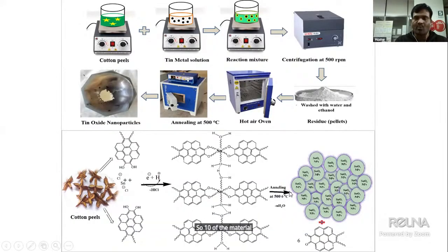The tin metal is going to be in the plus 2 oxidation state, and it is going to be reduced by the polyphenol. So the polyphenols form a complex in the presence of the tin material. Then, ultimately, on heating at high temperature, it will form the desired structure of the tin oxide nanomaterial. So this is the possible mechanism of the preparation of the tin oxide nanomaterial.